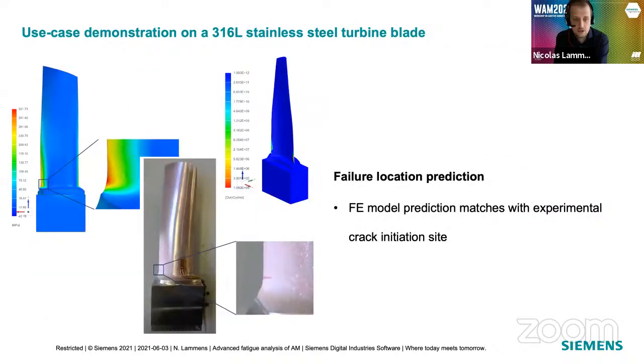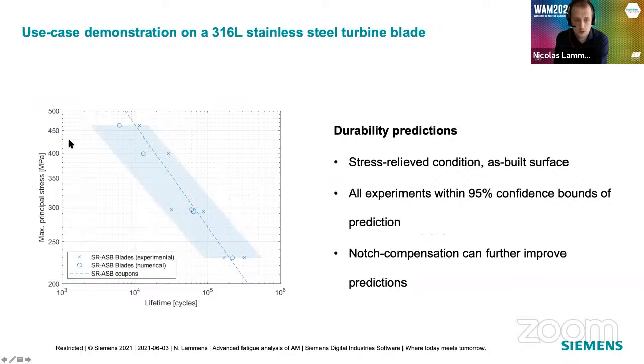And then if we look at the first results we got, if we just look at the durability results and the stress results, we see that failure is predicted at exactly the location where we saw it in each of the experiments that we did. But more importantly, if we look towards the actual numerical predictions, we see that we still get very good results. So on this plot here, you see the dotted line, which is the prediction that we did with our AM-aware durability solver for the component. And then the crosses that you see are the results from the experimental tests.